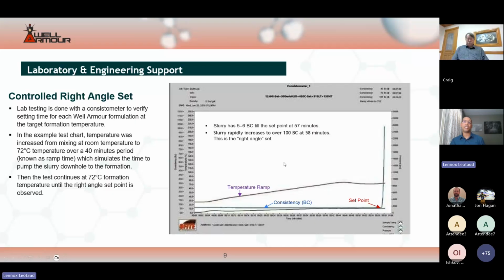This chart here is an example set time test done on a Well Armour slurry, in which the temperature was ramped from room temperature to 72 degrees C, simulating pumping the Well Armour from surface to the reservoir zone. And once the slurry gets to the reservoir zone, there's a dwell time where the temperature remains the same. And in this particular test, as you can see here, after about 57 minutes, the set point is reached, and you see the classic right angle set of the Well Armour slurry.